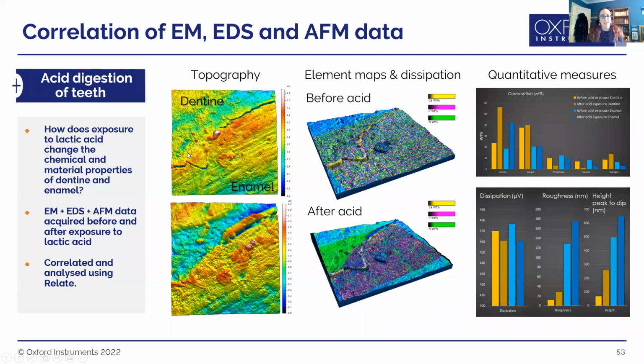So what we wanted to look at was the exposure of lactic acid and its effects on dentine and enamel in a tooth. We wanted to see how it affected the topography and also the dissipation, which is one of the measures you can get in an atomic force microscope. So basically the deformability of the material and how that was affected by the chemistry as well. So this meant we couldn't look at a coated sample because it would interfere with the AFM measurements.